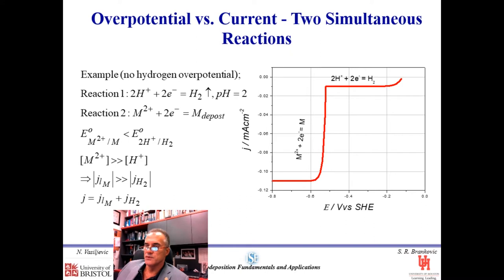In that case, what we are really looking at is a little bit more complex shape of the current over potential dependence. And in general, the goal is always to minimize the hydrogen evolution reaction with respect to metal deposition to increase the current efficiency. The current efficiency in this case is basically defined as the metal deposition versus the overall current that we run, and in general, the closer to one it is, the better it is. So for that reason, we try to keep the metal concentration always larger than the hydronium ion concentration, so that we can have a metal deposition current larger than hydrogen evolution current.